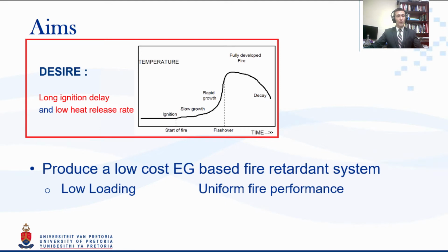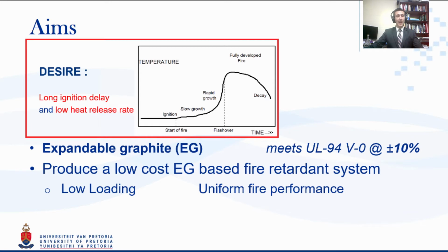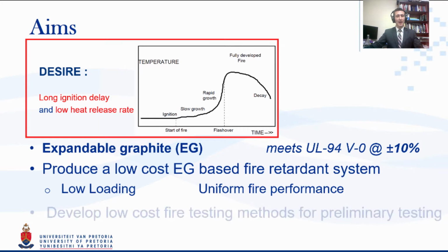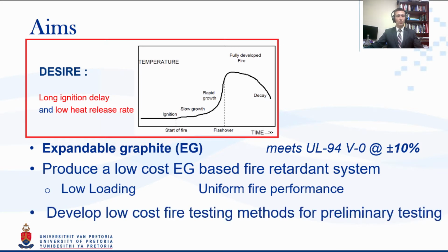So we identified expandable graphite because at a low loading of 10%, it's able to meet the UL 94 V0 international rating, which gives a very good indication on a small scale of some of the fire performance. But one of the things that we found in our earlier scoping research is that when this material at 10% load is put into a very large scale, into a plastic pallet, and burnt, there are actually some negative effects as well. What we want from it is uniform fire performance, but unfortunately initially it did not deliver that.